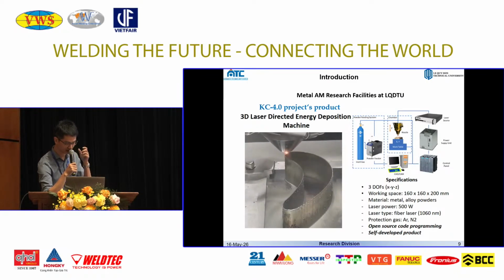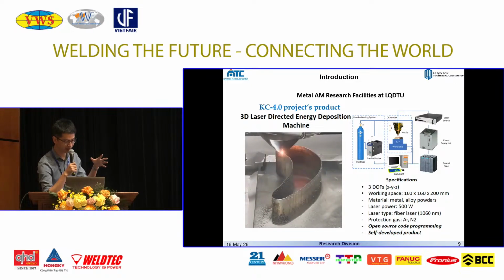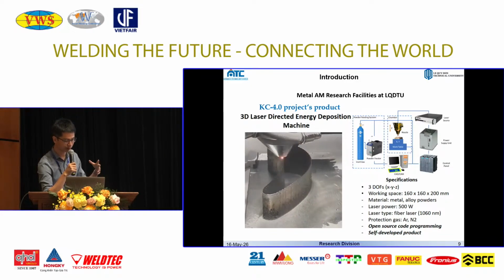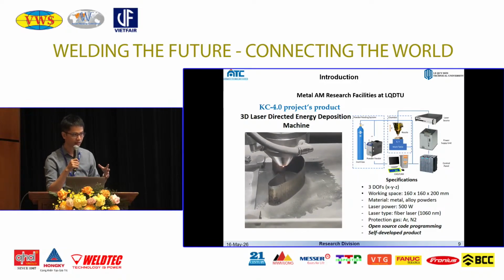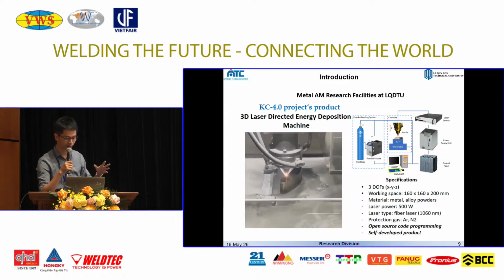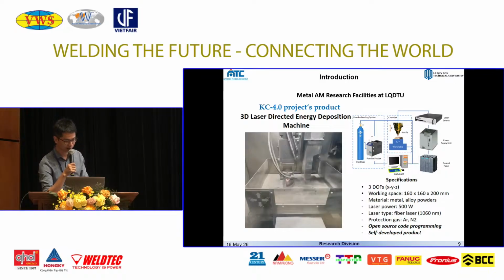Let's talk a little bit more specifically about this system. It is 3 DOF, that means we have XYZ axes, and the working space is pretty small because it is for experiments, 160 by 160 by 200. About the material, we can use any kind of powder in theory, of course if we can seal the chamber well. We also use a fiber laser with a power of 500 watts, and for the protection gases, we can utilize argon or nitrogen.